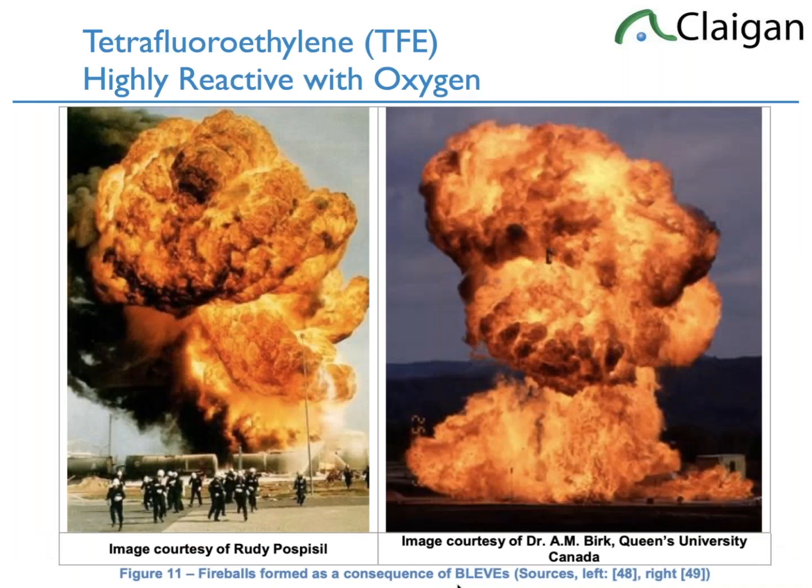or burns dramatically. So in your typical PTFE polymerization plant, more than half the equipment is around the safety of TFE, where TFE is normally stored with another chemical that keeps it from reacting with oxygen. When it's piped through the piping, most of the work is that it has to separate the chemical that stops it from reacting with oxygen, and then pipe it into the next reaction chamber without touching oxygen or air.